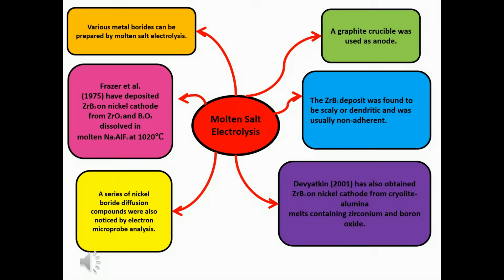1975, have deposited zirconium diboride on nickel cathode from zirconium oxide and boron trioxide dissolved in molten cryolite at 1020 degrees Celsius. A series of nickel boride diffusion compounds were also noticed by electron microprobe analysis. A graphite crucible was used as anode. The zirconium diboride deposit was found to be scaly or dendritic and was usually non-adherent. Devyatkin, 2001, has also obtained ZrB2 on nickel cathode from cryolite alumina melts containing zirconium and boron oxide.